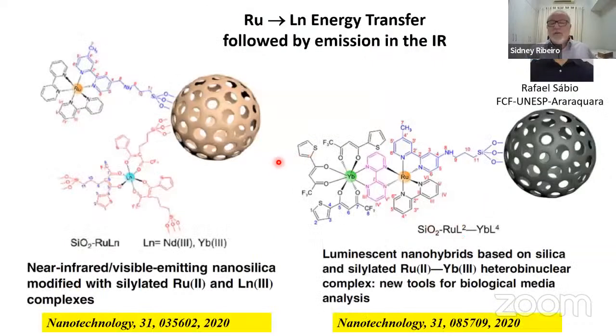These silica particles can also be modified with lanthanides emitting in the infrared, and they can be modified also with the same kind of complexes of ruthenium. By doing that, so you have here a silica particle, ruthenium absorbs strongly in the visible. So a ruthenium will absorb visible light and will transfer the energy to the lanthanide complexes emitting in the infrared, with a lot of different applications for this material.